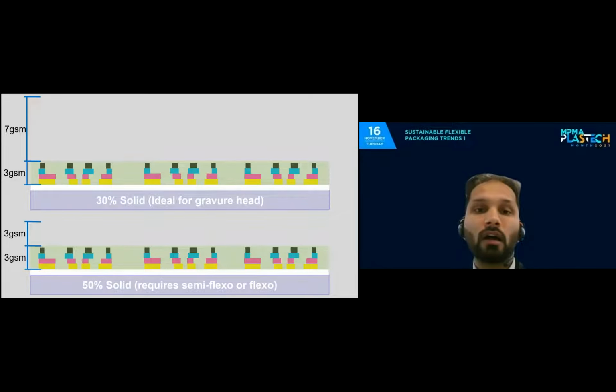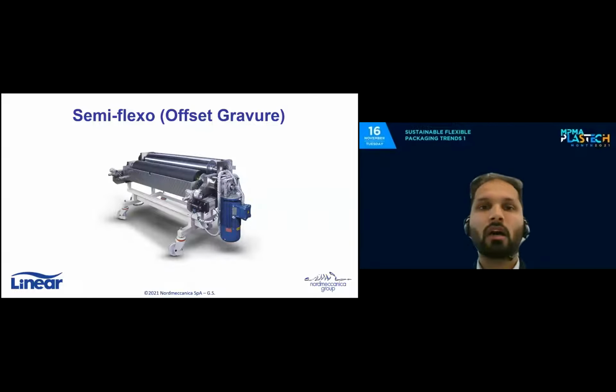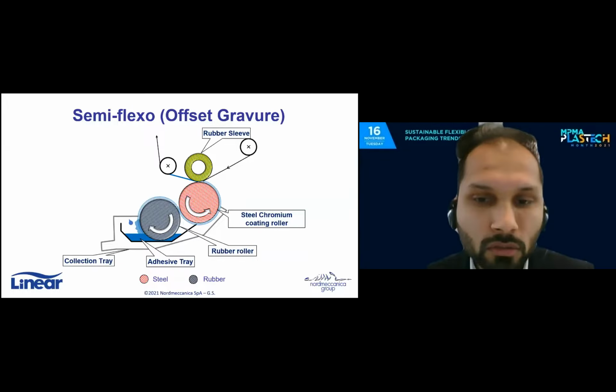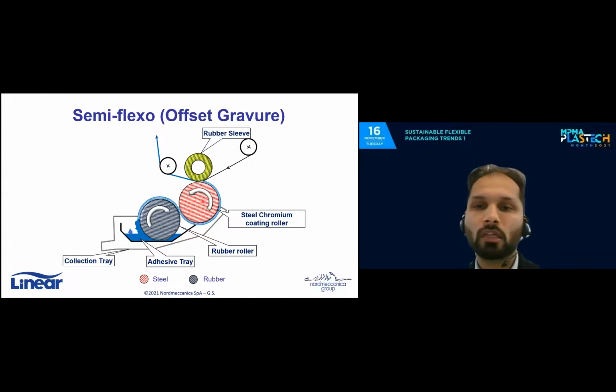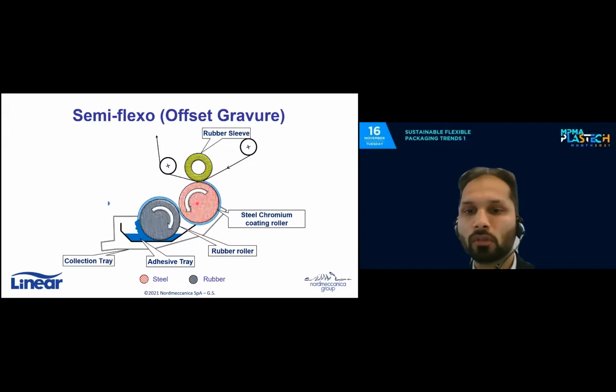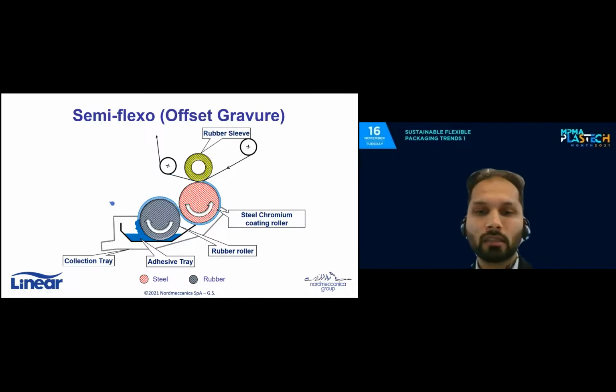The advantages of these are low energy consumption and better optics of the lamination compound. And in order to apply these high solid adhesives, there are specific coating heads that can be used. One of these is the Nord Mechanica Semiflexo. The Semiflexo is made of one rubber roller, one steel chromium coating roller, and one impression roller. The rubber roller collects the adhesive from the adhesive tray and transfers it to the steel chromium coating roller. The beauty of this system is that both the rubber roller and the steel chromium roller are smooth rollers. By simply playing with the speed of these two rollers, it is possible to adjust the coating weight.